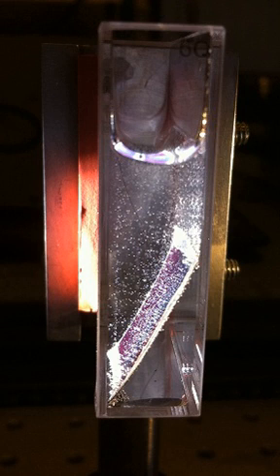Cobalt compounds such as cobaloximes are some of the best hydrogen catalysts, having been coupled to both metal-containing and metal-free photosensitizers. The first H-cluster models linked to photosensitizers, mostly ruthenium photosensitizers, but also porphyrin-derived ones, were prepared during the early 2000s. Both types of assembly are under development to improve their stability and increase their turnover numbers, both necessary for constructing a sturdy, long-lived solar fuel cell.